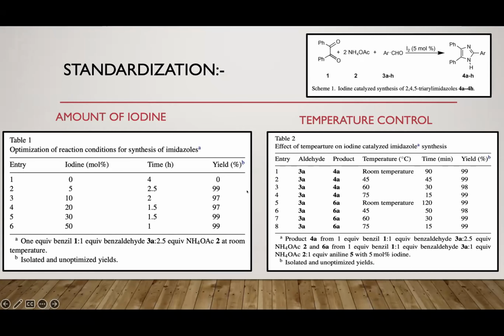In the absence of iodine, you can see from the table that we carried out the reaction for up to 4 hours, but only traces of product were obtained. With just 5 mole percent, we were able to get a good amount of product, which is 99%. With an increase in the mole percent of iodine, we were able to reduce the duration of the reaction, but we thought of using 5 mole percent as the lowest concentration of iodine for the synthesis.